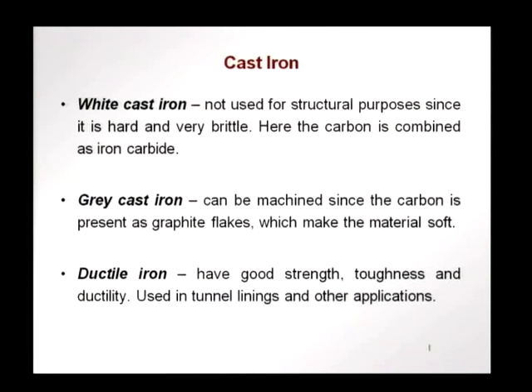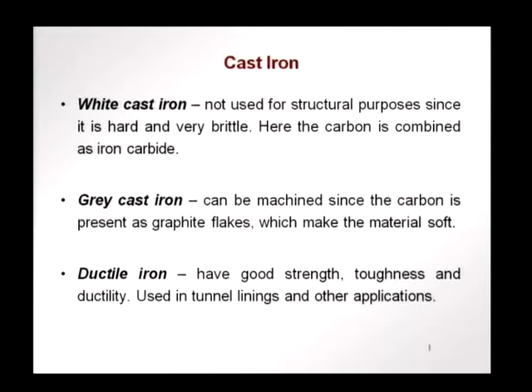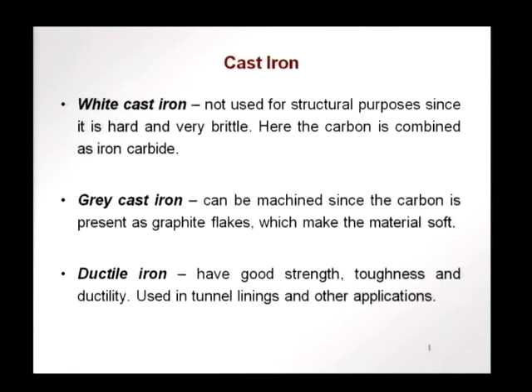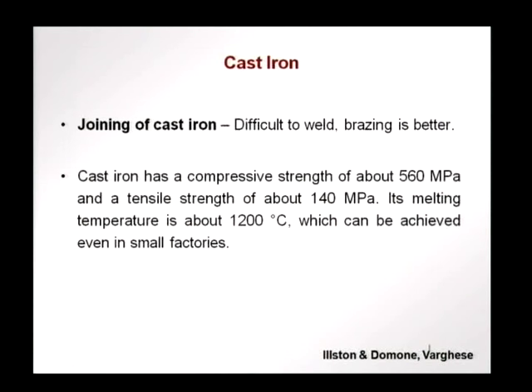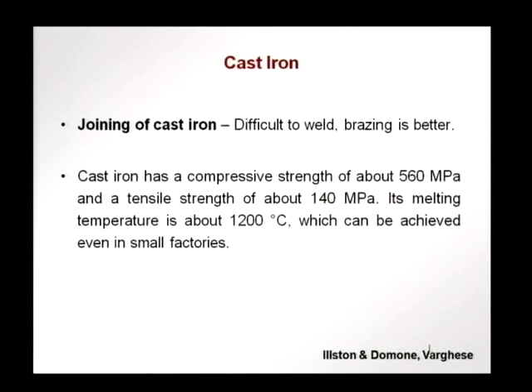Cast iron is a material that is brittle, used for casting, not for hot working. White cast iron is very hard and brittle and is not used for any structural purposes. Gray cast iron can be machined; it has carbon presented as graphite flakes. This makes the material soft, suitable for machining. Then we have ductile iron which has good strength, toughness and ductility — it is used for tunnel linings and other mass applications. Some limitations of cast iron come up in the joining processes. Cast iron is difficult to weld due to its brittleness. Brazing is better, where we introduce a second metal to connect pieces without taking the cast iron to melting temperature.